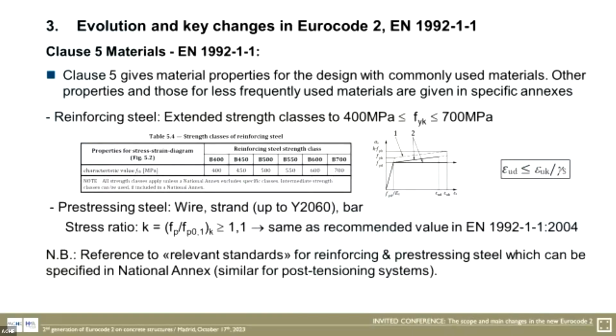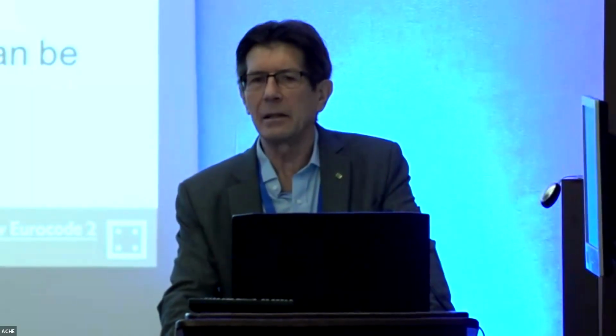Reinforcing steel, also here we have increased the range of strength classes up to 700. Similar for pre-stressing steel, a slight increase for strand. Otherwise, design assumptions are the same. See here the stress-strain diagrams for design, that's the same as in current Eurocode. We have a slight issue because there are no commonly accepted standards for reinforcing and pre-stressing steels at this time. So that's why we make reference to so-called relevant standards when we refer to these materials. This allows the countries to specify the standard which applies in their country at this time and until harmonized standards will be available in Europe for reinforcing and pre-stressing steels. Alternatively, rather than referring to a standard, countries can also give the properties directly in the national annex.